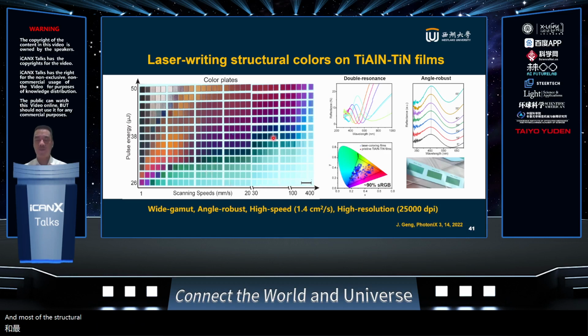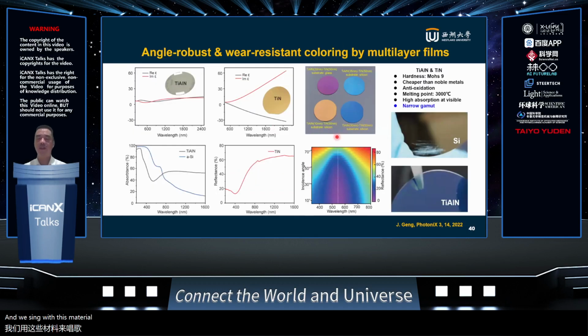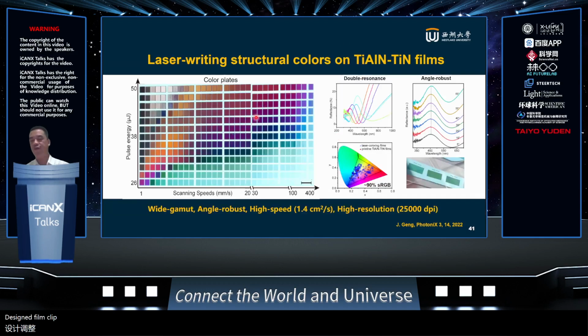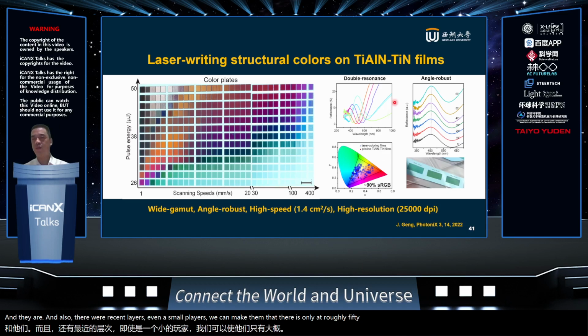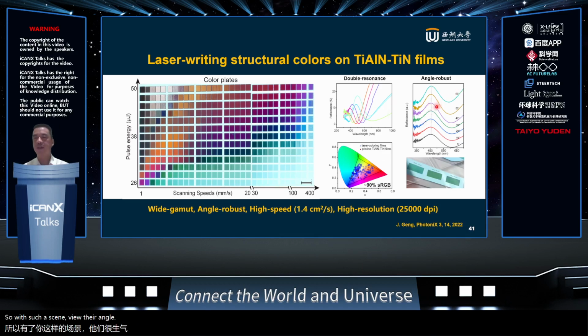With different designs of films, we find it's possible to cover almost all the colors. Most of the existing structural colors can only cover 10 to 20% of the sRGB color space. And we think with these material systems, when we design the film carefully, we can actually cover almost all colors, including black and white, and red, green, blue, yellow, almost anything. So you can see from here, it covers almost the whole space, about 90%. And this is due to the double resonance. And they are very thin layers. Even though it's multi-layers, we can make them only roughly 50 nanometers. So with such a thin film, they are angle robust. At least viewing from 0 degrees to 60 degrees, the color does not change significantly.